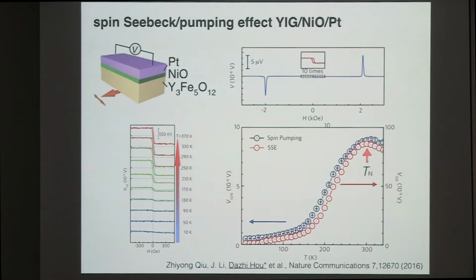And actually, we can also see the spin Seebeck effect when we do spin pumping, because if you put microwave on a sample, you effectively heat the platinum layer a little bit. So it automatically gives you a temperature gradient across the z direction. If you zoom in on this very small area, you will see the spin Seebeck effect. You can extract the spin Seebeck value and plot it against the temperature. You will see that the behavior is nearly the same as the data from spin pumping.